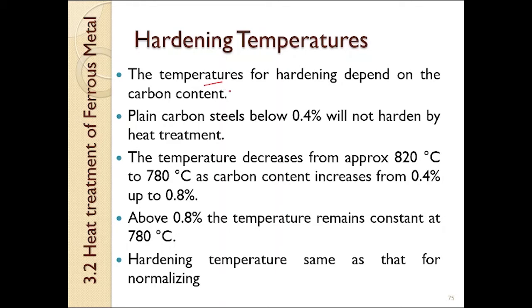The temperature for hardening depends on the carbon content. Plain carbon steel below 0.4% will not harden by heat treatment. The temperature decreases from approximately 820 degrees Celsius to 780 degrees Celsius as carbon content increases from 0.4% up to 0.8%. Above 0.8%, the temperature remains constant at 780 degrees Celsius. The hardening temperature is the same as that for normalizing.